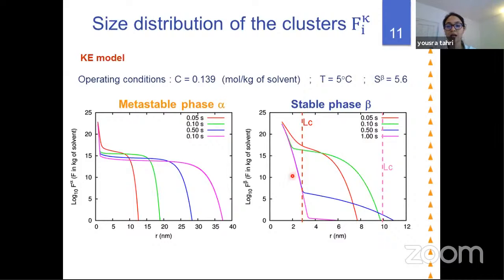the critical size was around 3 nanometers, and you can see from the number density that we had a certain number of crystals, of clusters that were supercritical. It means they had a size that is higher than the critical size. Then at 1 second, the critical size is almost 10 nanometers because the supersaturation was consumed. And here we can see that all the clusters that we have are under critical.